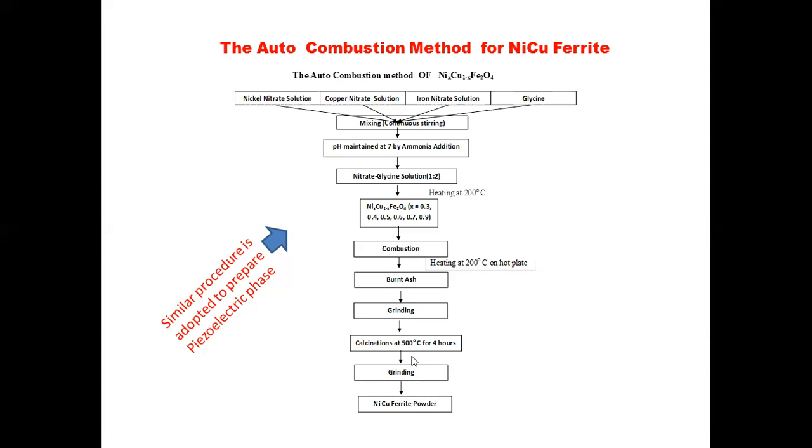But the advantage of this auto combustion method is that you are getting a very, very fine powder, and the time used to synthesize the compounds is also very, very less. So that is the biggest advantage of this auto combustion method. And nowadays, most researchers use this auto combustion method to prepare different composite materials or other materials.